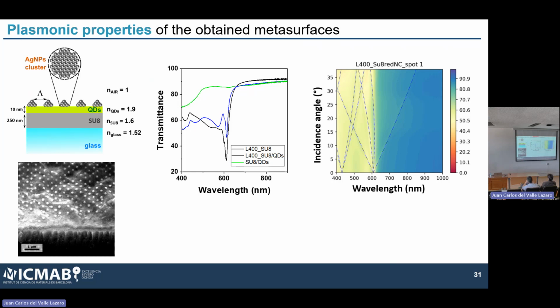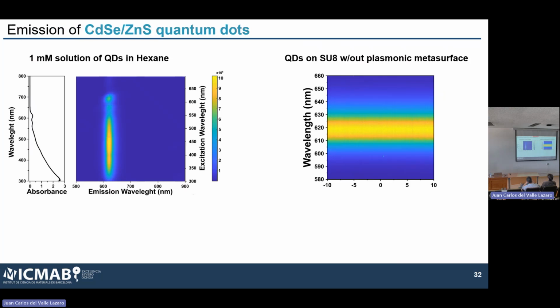So once again, here you have the optical characterization with our sharp resonances and our contour plot showing the diffraction line. And this is basically the emission characterization. This is on quantum dots alone. So when you see here, these are just quantum dots without the particles. This is in solution, just to see where the emission is. And here is on the thin film.